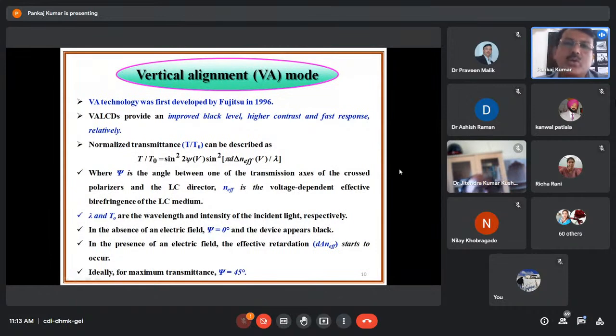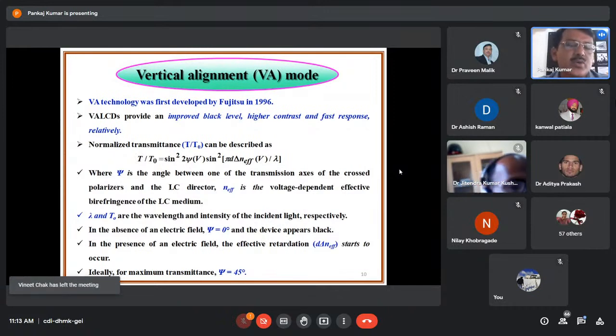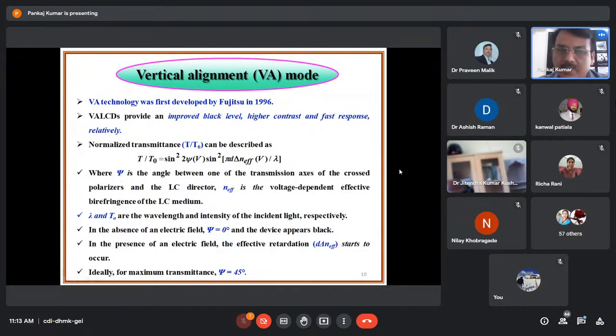So scientists worked on the vertical alignment mode, and VA technology was first developed by Fujitsu in 1996. VA LCD, the vertically aligned liquid crystal display, provides an improved black level, high contrast and relatively fast response. In vertical alignment mode, the normalized transmittance can be described as T by T naught equals sine square 2 psi, sine square pi d delta n effective by lambda. You can see in these equations that psi is the angle between one of the transmission axes of the crossed polarizers and the liquid crystal director, and delta n effective is the voltage dependent effective birefringence of the liquid crystal medium.